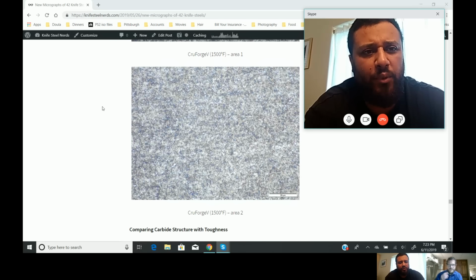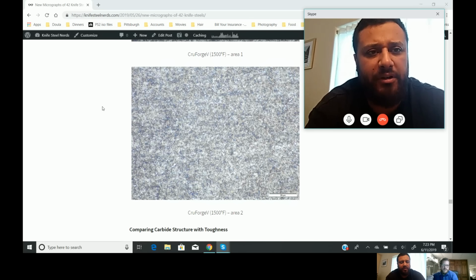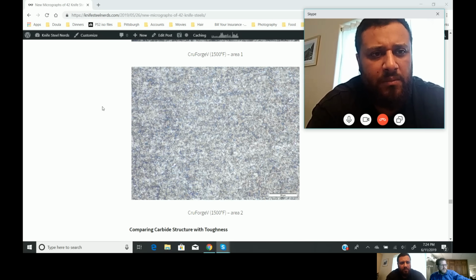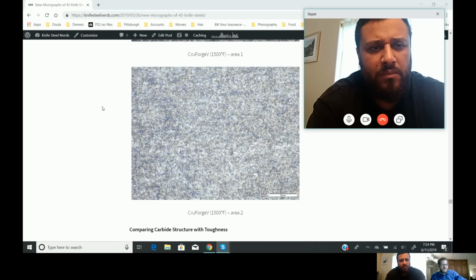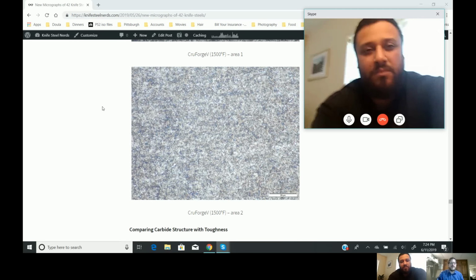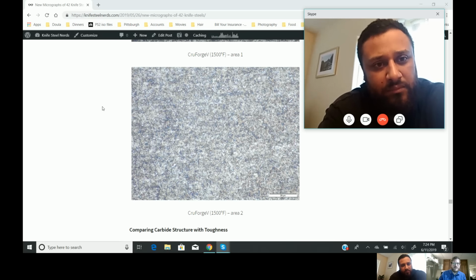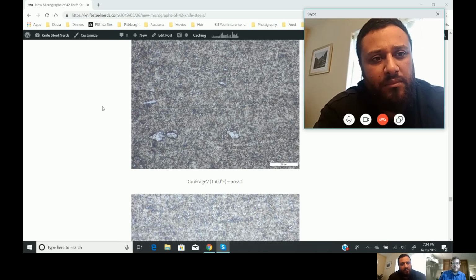So now this sample was forged, right? Do you think forging this steel helps dissolve some of those bigger clumps that are inside the material? Yeah, it can, but the process at the mill is reducing it by a lot more than you would in your home shop, even under a power hammer with heavy stock. So the carbide size is going to be set primarily by the mill, and you are likely to mostly just make the carbides bigger due to lots of time at high temperature, where they heat it up once and they roll it out in just 1 or 2 heats. And they're supposed to have well controlled schedules for rolling where they got it dialed in to lead to the best rolling performance and the best final structure. So I wouldn't count on making it finer through forging.